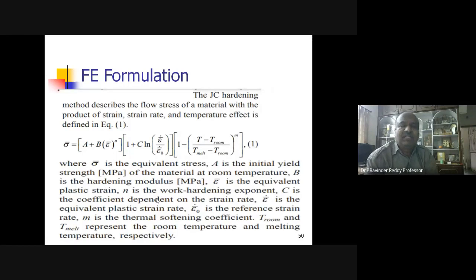When you use the models already in LS-DYNA, there are 64 material models you have. Even Abaqus is similar. We can adapt some of the material models so that the coefficients will be available. These material properties we can assign, and the indices we need to specify. Typically, the Johnson-Cook method describes the flow stress of the material with the strain rate and temperature effect. So there are going to be the constants A, B, and C, and ABC are given in the material strength values.